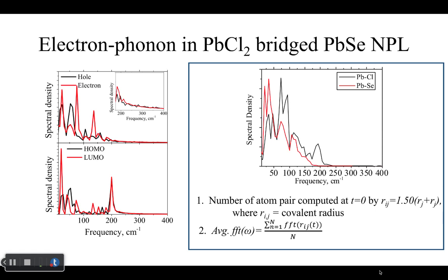In this case, I would say you probably need to figure out these atoms not at initial time, but at 0 Kelvin, just to figure out which really create these bonds, right? Because at initial time, you equilibrate your system, so it's very arbitrary. Some of them might already be out of this bond, but since they oscillate, they might come back to it, right? So I would say you need to apply this to your 0 Kelvin structure, then you have a list of atoms contributing to these bonds, and based on these indexes of atoms, you run the dynamics.